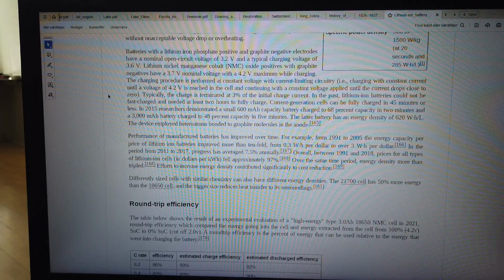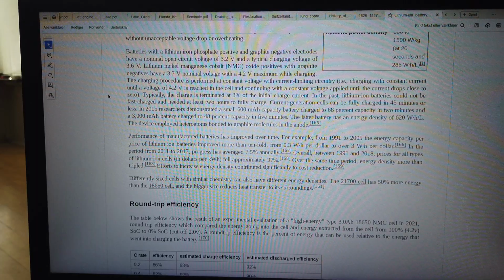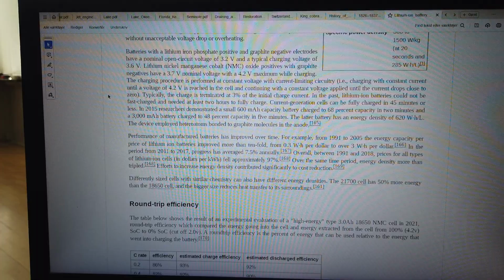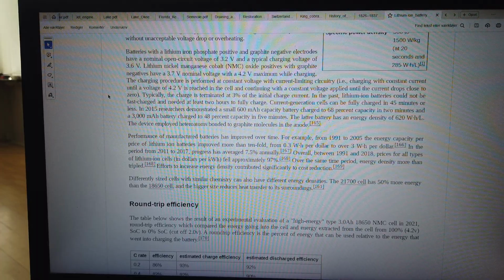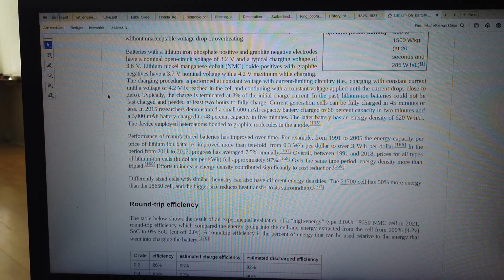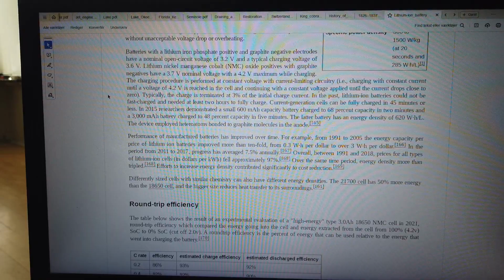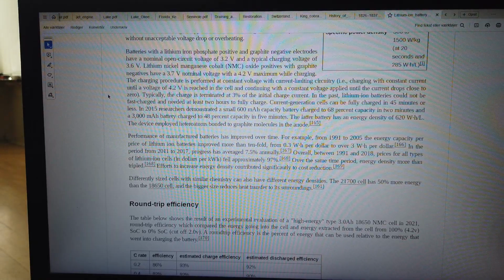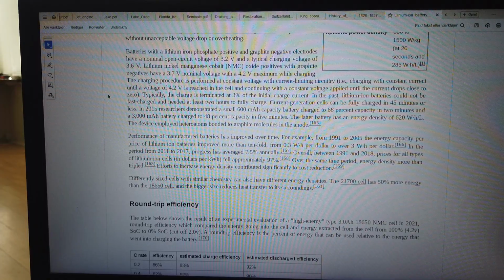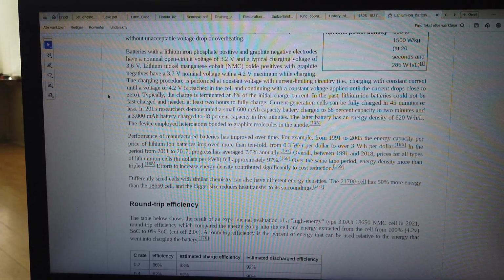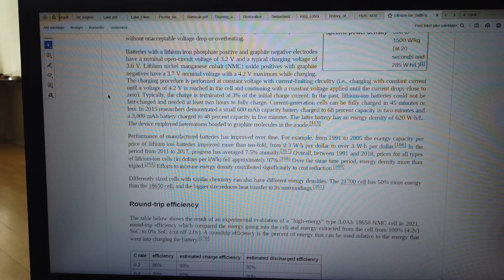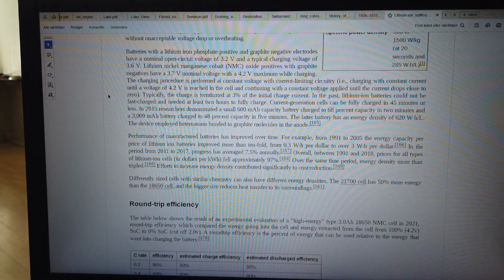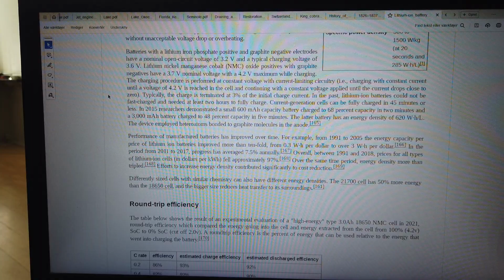In the past, lithium-ion batteries could not be fast charged and needed at least 2 hours to fully charge. Current generation cells can be fully charged in 45 minutes or less. In 2015, researchers demonstrated a small 600 mAh capacity battery charged to 68% capacity in 2 minutes and a 3000 mAh battery charged to 48% capacity in 5 minutes. The latter battery has an energy density of 620 W·h/L. The device employed heteroatoms bonded to graphite molecules in the anode.